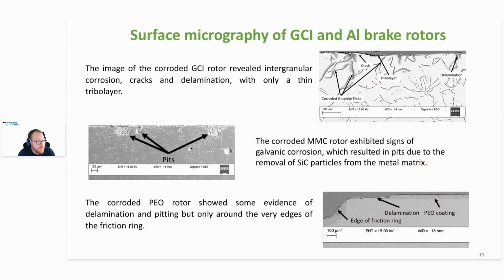Looking at the sectional micrographs taken through the surfaces of the three rotors at the end of the test sequence, it's apparent that the graphite flakes near the surface of the grey cast iron rotor have been affected by corrosion exposure. You can see those pits there. The section through the metal matrix composite surface reveals that the pits have been formed by the removal of the silicon carbide particles due to corrosion effects of the aluminium matrix. In contrast, the vast majority of the PEO rotor surface remained intact, although there is some evidence of pitting and delamination at the very edges of the friction ring, where the PEO process is less effective.